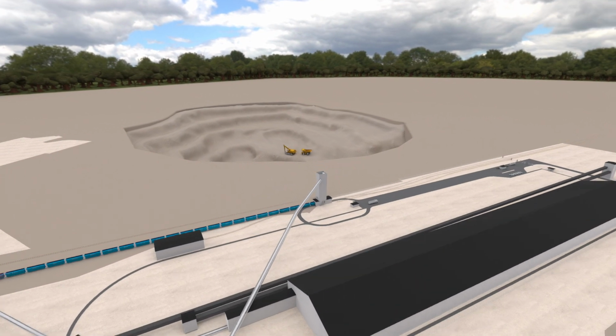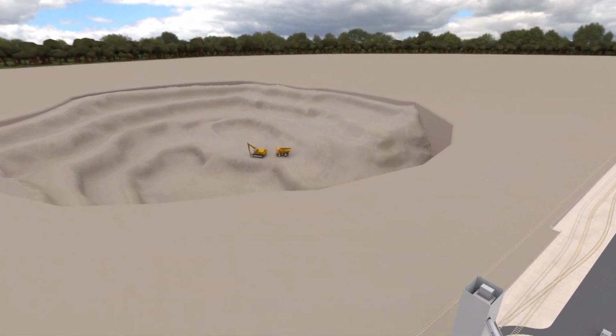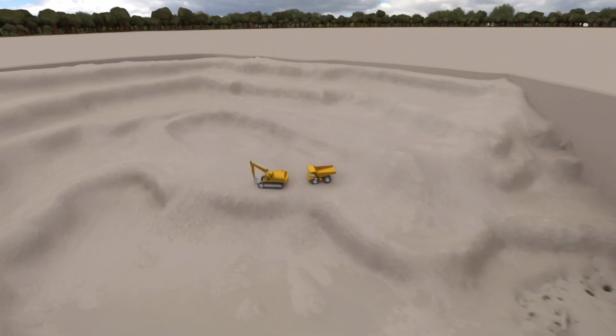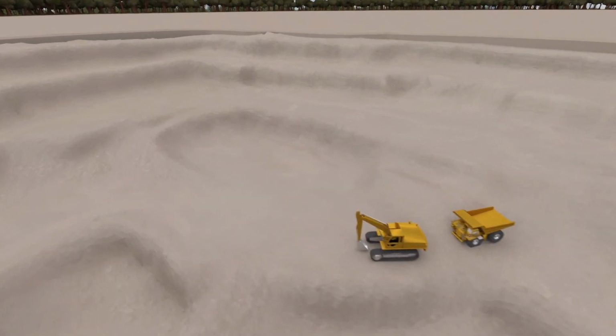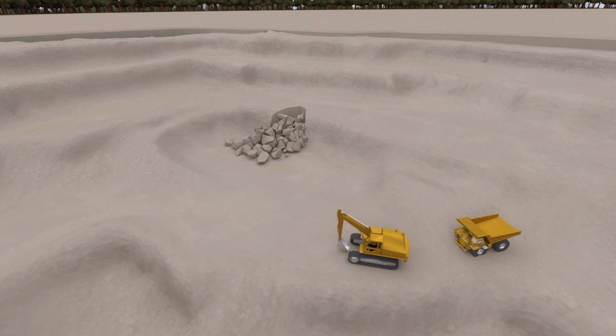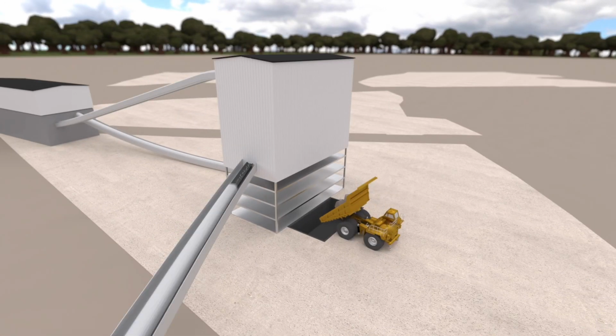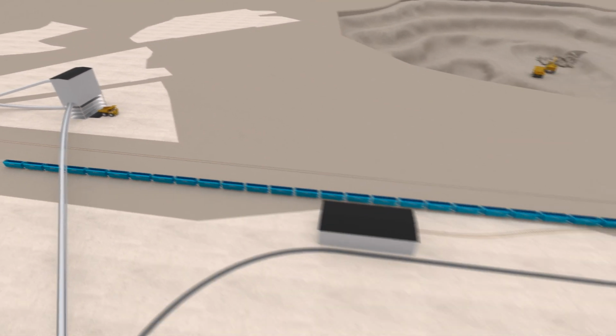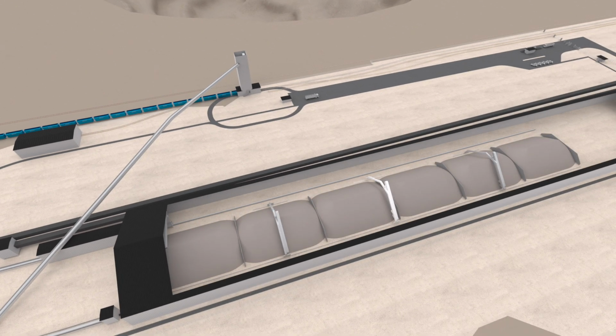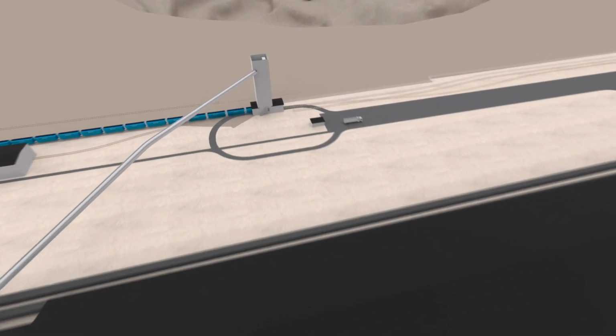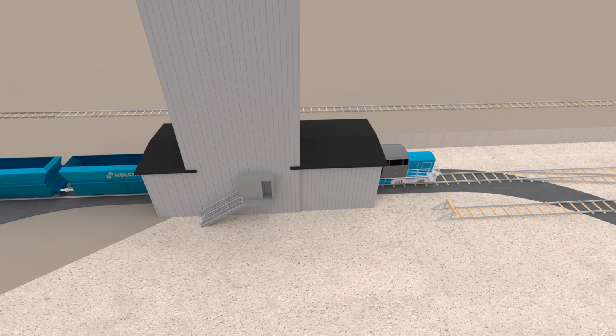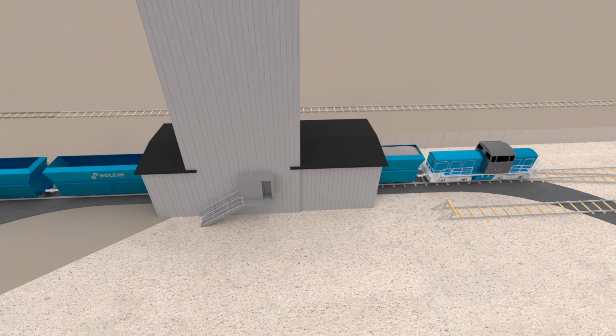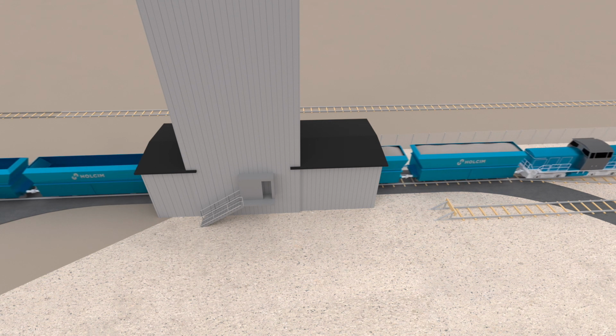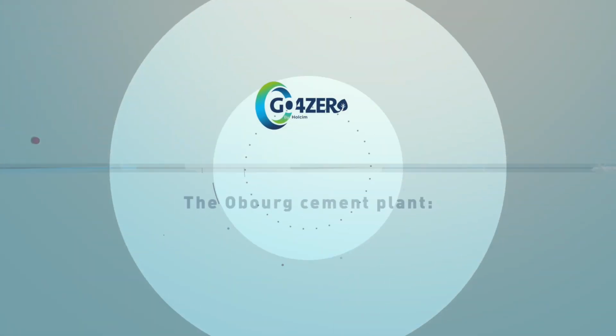The initial phase of our dry manufacturing process begins in our quarries in the Tournai region. Limestone is extracted here by blasting. The blocks are collected and crushed in successive stages until they reach an approximate size of 10 centimeters. They are stored in a hall before being shipped by train to the Obourg plant. Each train is approximately 400 meters long and can transport nearly 2,200 tons of materials.